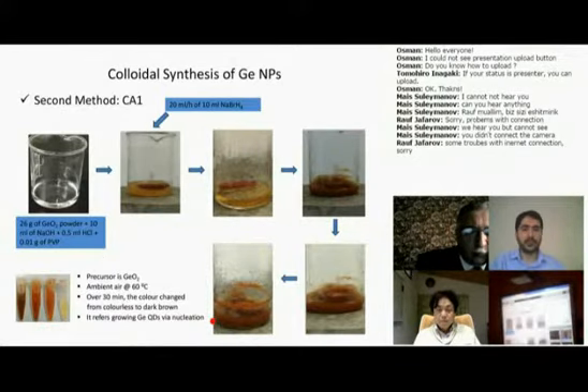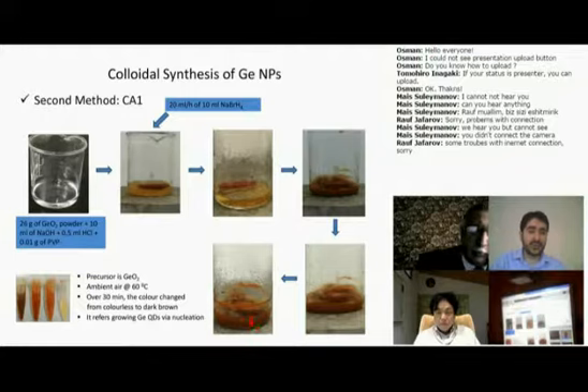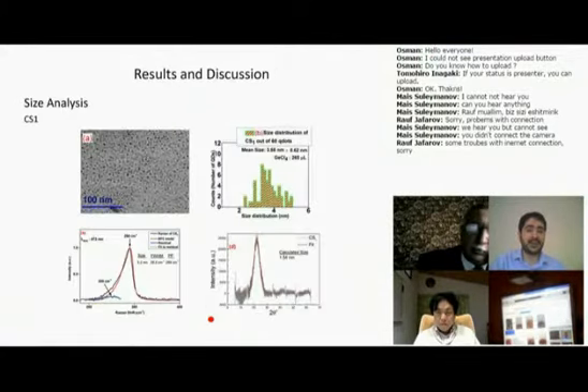like in liquid form. The second method is the aqueous method. Also, it's benchtop. It's very easy to synthesize, as you can see from the picture. We have our mixture of samples and elements, like here, and I am using a magnetic stirrer at 60 degrees Celsius, a little bit above room temperature, and I am stirring it for about an hour. After that, I'm able to obtain my particles like this, here in powder. I can also suspend them in methanol as a liquid.